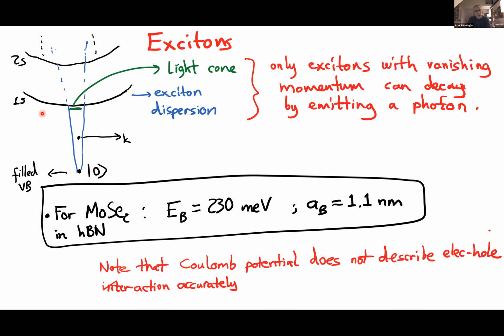So this 1s, 2s assignment follows the Coulomb potential, but we also know that the Coulomb potential actually does not describe the electron-hole interaction accurately. One should really resort to a Keldysh potential because of the strong in-plane screening. And some numbers: if molybdenum diselenide is embedded in boron nitride, the binding energy is 230 milli-electron volts, and the Bohr radius is about 1.1 nanometers. So if you're familiar with excitons, this is still a Wannier exciton, but not so far off from a Frenkel exciton, which is typical in molecular systems.